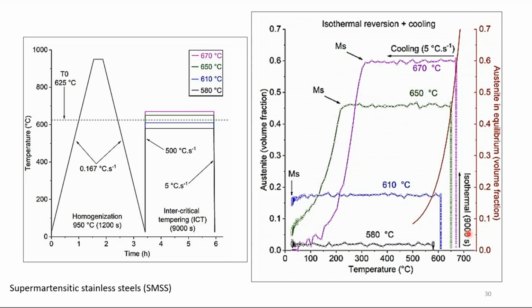The isothermal, let's start from the right to the left, okay? You have the austenite volume fraction, calculated or measured, on the left y-axis, and on the right y-axis you have the austenite in equilibrium calculated by Thermo-Calc, and below you have the temperature. So you start your isothermal treatment here on the right, going to the left. The isothermal treatment goes to the higher temperature until this point that reaches the equilibrium of the austenite. Calculated, it's perfect. For the other temperature as well, 650.